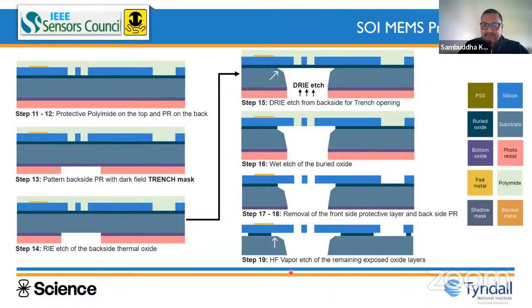So this is where they use HF vapor. It is a hydrofluoric acid vapor that is used to etch away the exposed oxide, buried oxide, wherever it is there. And that creates some undercut inside the buried oxide as well. Like here, as you can see, it was etched up to this, but after the HF vapor etch, it etches more, and there is an undercut that happens here, and that's why it goes a little inside. That's why there are certain design rules that will be discussed, on how much it goes inside and how much you need to keep, so that unwanted areas don't become suspended.